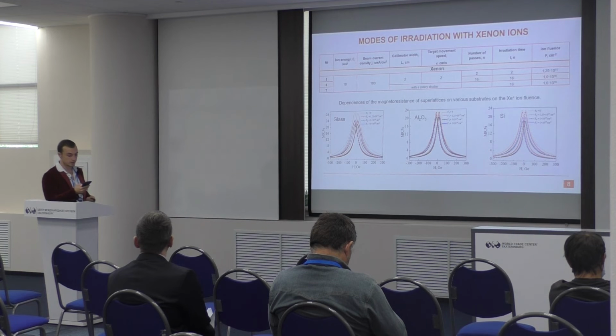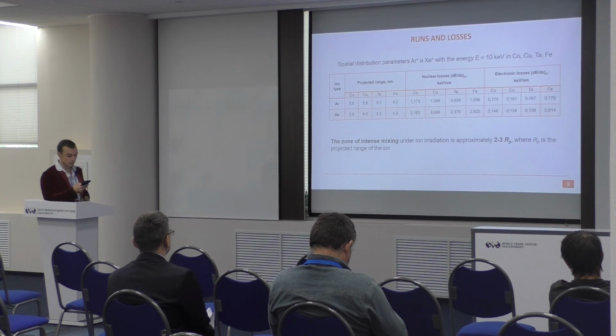It can be assumed that the degree of change in the structure of multilayers and their interfaces caused by the action of argon and xenon ions with the energy of 10 keV at the fluences used is insufficient for a radical change in the structural state of the studied superlattices. According to the literature and the data obtained by us, the decrease in the magnetoresistance of superlattices is mainly due to the process of mixing atoms of layers of different types and change in the states of the interfaces.